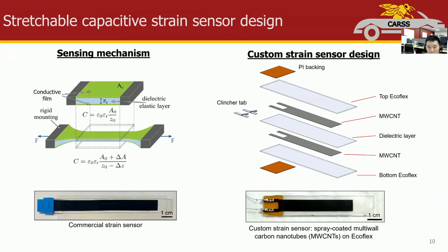Our strain sensor is based on parallel plate capacitive sensing mechanism. When the two stretchable conductive films are stretched, the overlapping area will increase and the gap between the two films will decrease, thus increasing the capacitance between them.